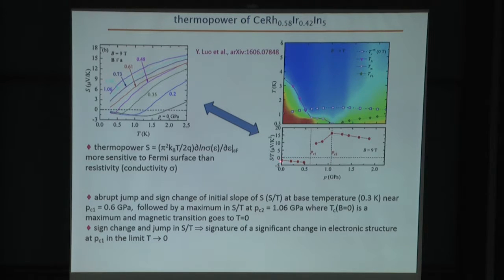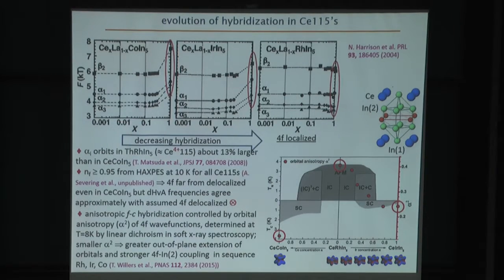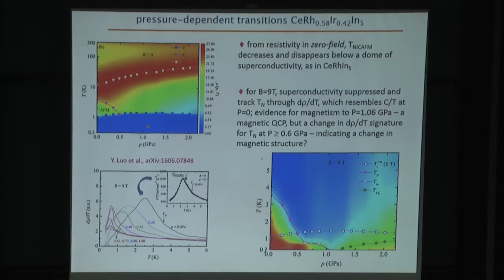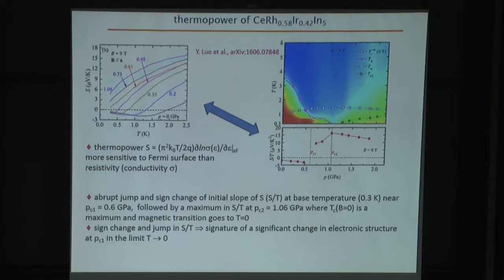And what we see is that there is a qualitative change, not only in the sign, but in the magnitude of the thermal power divided by temperature at this pressure, where there is a well-defined change in the pressure dependence. Sorry, wrong buttons. Let's go back. There's a huge anomaly in the thermal power divided by temperature at this pressure, followed by a maximum in the thermal power divided by temperature, where the magnetic transition goes to zero. So this huge change in thermal power, because the thermal power is so sensitive to details of electronic structure, implies that there is a qualitative change in electronic structure at this pressure here.